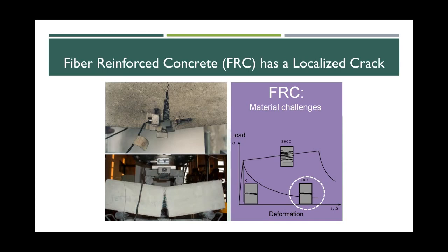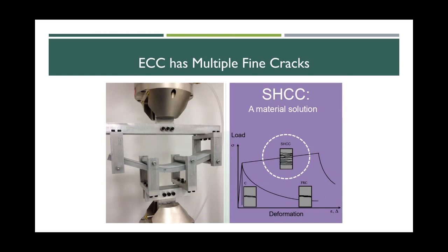But it still has a localized crack. And you see that the crack was just centered and it was delayed by fiber bridging. So of course it has some deformation, but at the same time, the load cannot be sustained. So to improve that, we have the ECC that has multiple fine cracks. Not only does it have a large deformation, it maintains a load at a certain level.